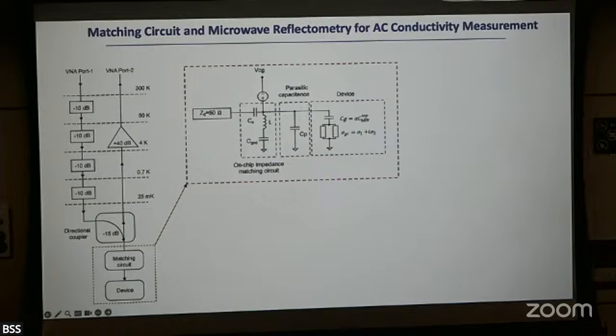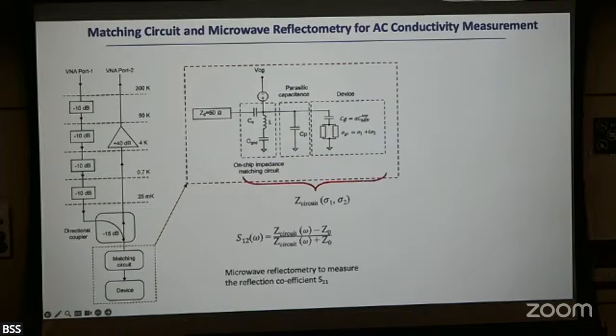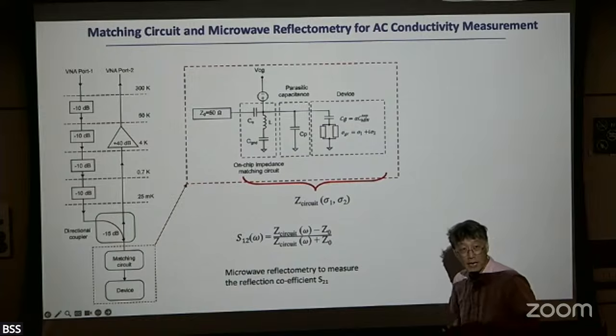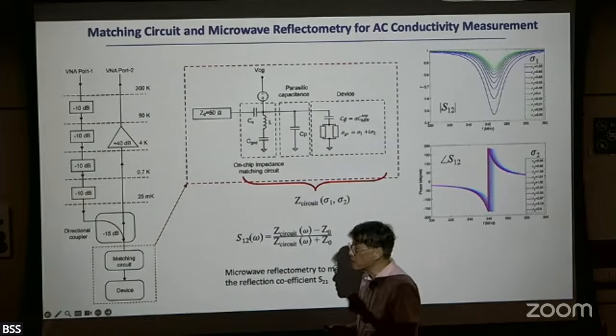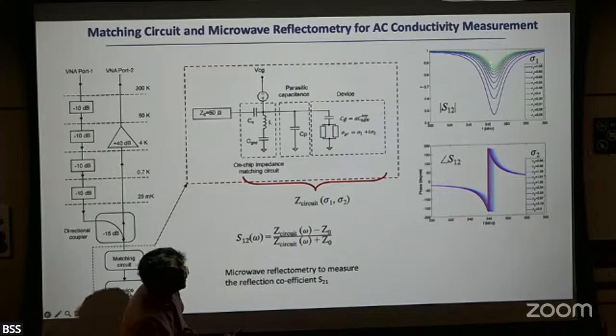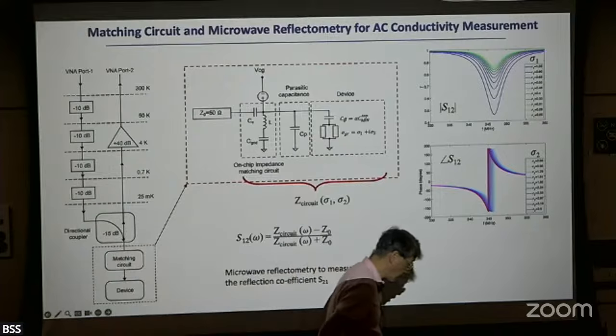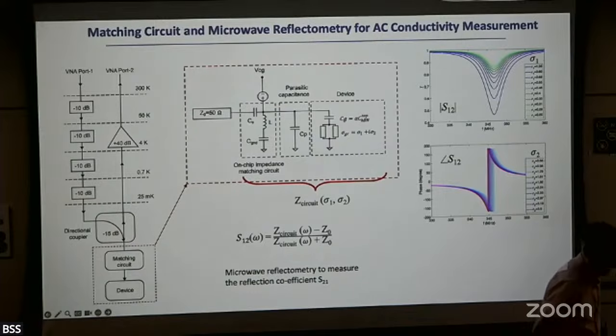And so that's why you have to redesign your matching circuits and simulate them. What are the right elements you just put up there and so on. But the idea there is, if you do the right matching, when the sample capacitance changes, the resonance curve that you get in the RF reflectance changes: the amplitude, the resonance frequencies, as well as the width all sensitively depend on the change of the capacitance that you are measuring. So that's the way it worked out.